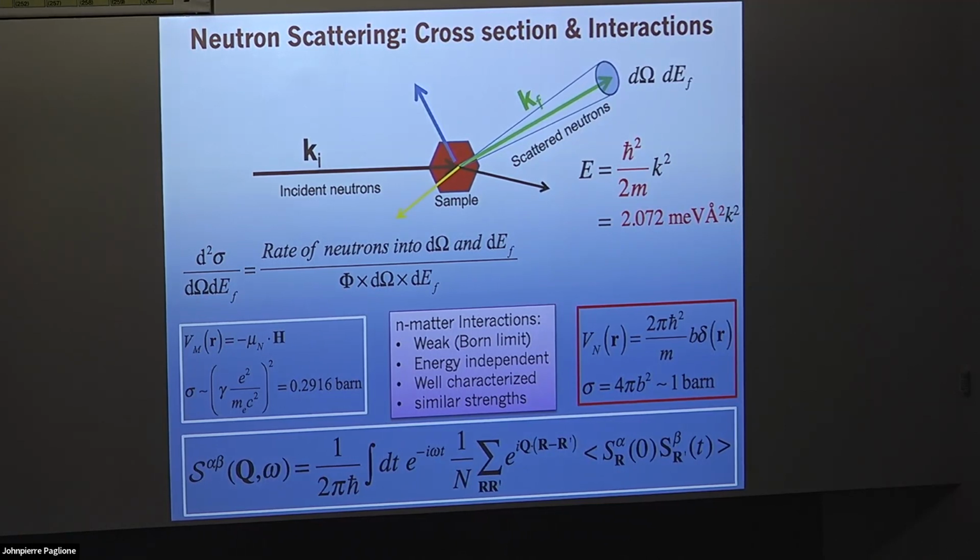But if you look at this part of it, then that is what we call a spin correlation function. It involves the correlation between spins at two different sites of the material at two different times. That's the thing that we can actually probe with neutron scattering, not as a function of position and time, but as a function of momentum, which is the conjugate variable to position, and energy, which is the conjugate variable to time. So when we look at these maps in wave-vector and energy space, from years of looking at these data, we've become familiar with how that relates down to this correlation function, which somehow encodes a lot of the interesting collective physics of materials.